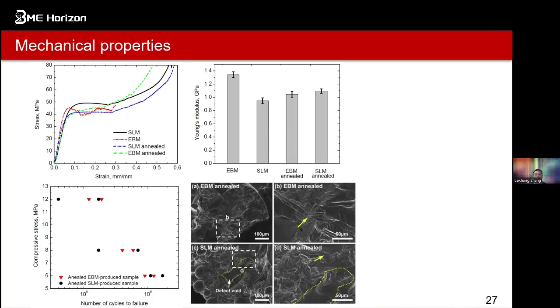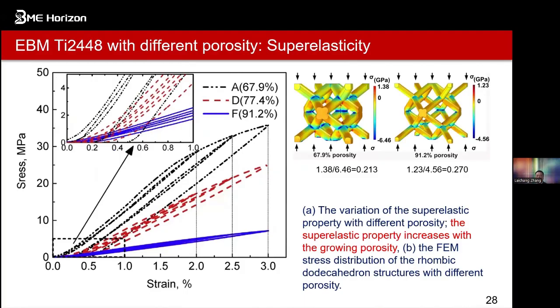We also produced a lot of structures with different porosity levels. As we mentioned, the porosity can be controlled. We produced from 20, 30, and of course up to 90 percent. You will see all this beta titanium has superelastic properties, even with different porosities. For easy reading, we only show the superelasticity of the lattice structures with porosity levels 68, 77, 77, and 91. With increasing porosity, you can see the superelasticity is increasing because they are fully recovered. This one still has some gap, which means still plastic deformation of these structures.